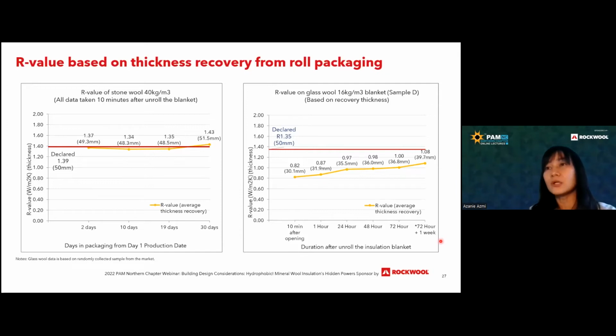As opposed to Glasswool, I do note the Glasswool data that we take is a randomly collected sample from the market. This is actually 16 kg. For this sample, we open it up, let it sit 10 minutes, and measure. The same sample, after 1 hour, we measure again. After 24 hours, after 48 hours, after 72 hours, and after 72 hours plus 1 week, we measure again. You will see here, even after 1 week, it does not go back to the original nominal thickness as you declare. In a way, it will compromise the performance of the overall U value.